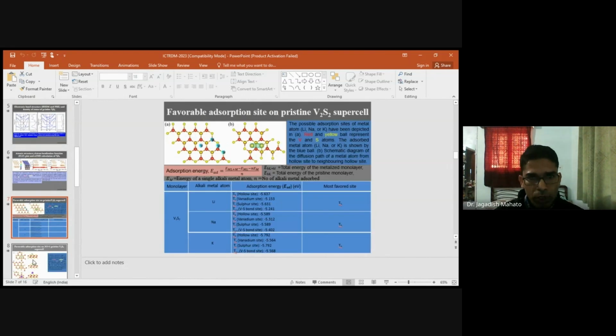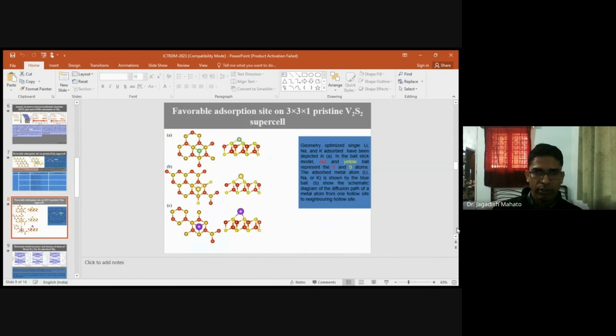Then we calculate the absorption energy using this formula for the metal ion. We take 3 different metal ions: lithium, sodium, and potassium, at different possible absorption sites. We take the hollow site, the site on the vanadium, the site on the sulfur, and also above the vanadium-sulfur bond. From the absorption energy calculation, we found that the hollow site is the most favorable for all the metal absorption cases, that means for lithium, sodium, and potassium. This figure shows the geometry optimized single atom absorbed on the most favorable site, that is the hollow site.